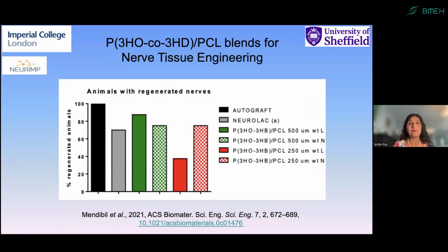And finally, when we compared them across all the types of samples that we observed, we found that the blend of P3HO-HD with PCL was almost the best, except for the autograft, which obviously is a real nerve, and one can't expect that we are absolutely the same as an autograft. There was no significant difference, but we could see that it was much better than Neurolac, which is the current commercially available nerve guidance conduit to the surgeons.